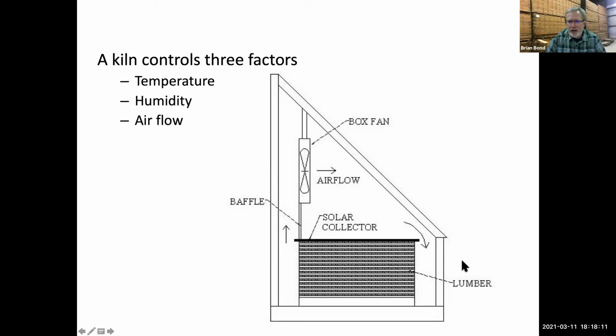And that's exactly what we do in a solar kiln here. You know, you've got a collector that lets the sun in. We heat this airspace, so we've got some temperature. We got a fan in here to control airflow. And then my humidity actually drops. I can control my humidity by the amount of water coming out of the lumber. I have some vents on the back I can open if I want to drop it, or I can just use the raising of the temperature to drop that relative humidity.